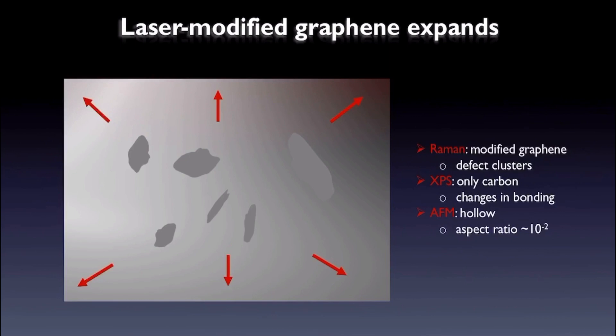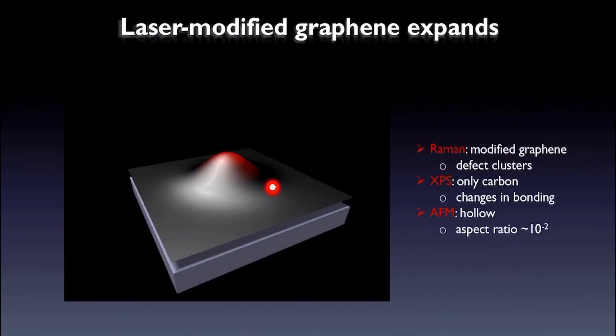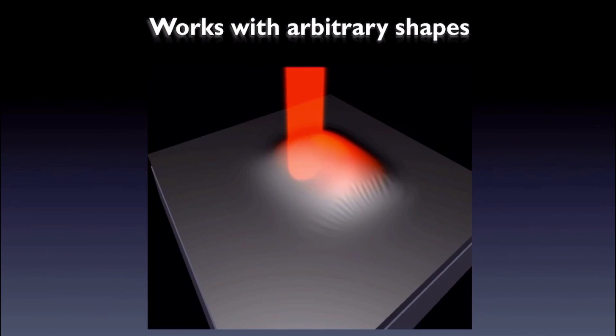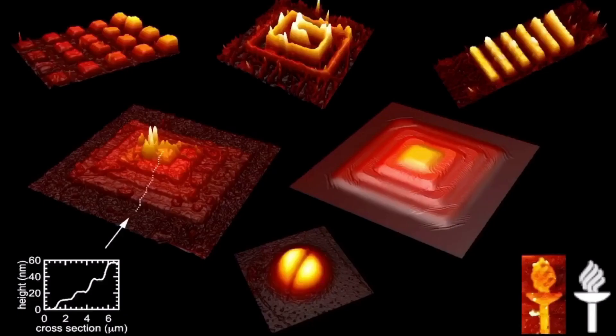Note, by the way, that the blister visualizations here are a bit exaggerated, as the aspect ratios of the blisters are typically in the range 10^-2. At any rate, the forging technique is such that the blistering follows the time-integrated laser intensity patterns, whereby we can draw blisters of arbitrary shapes. And this is also what we have done previously. We forged square meshes, spirals, gratings, pyramids, and more.